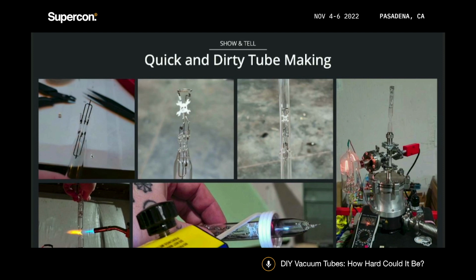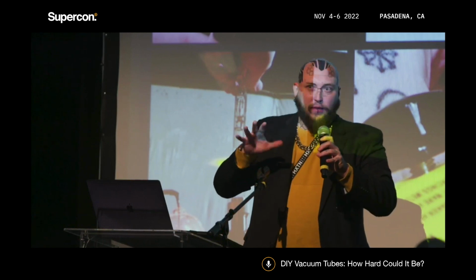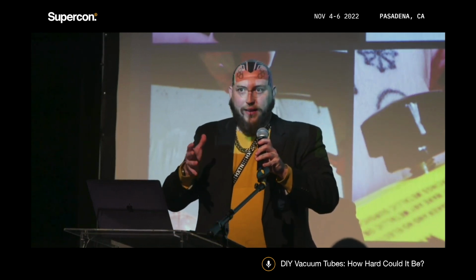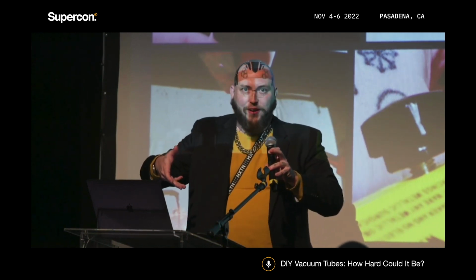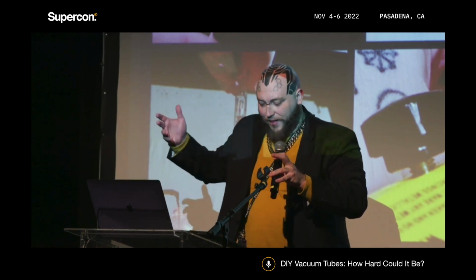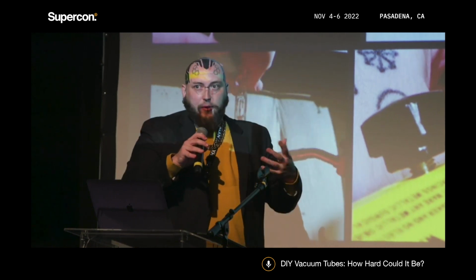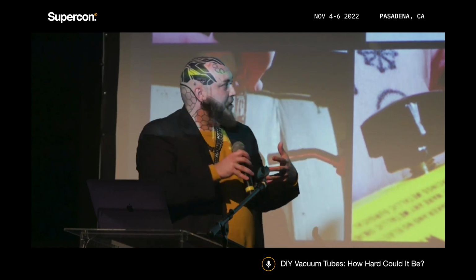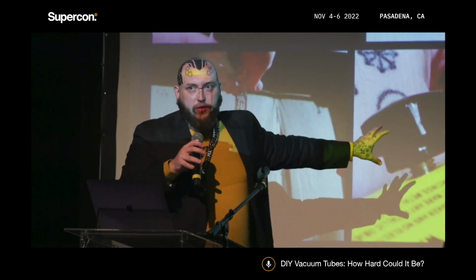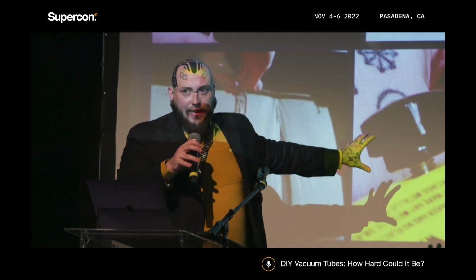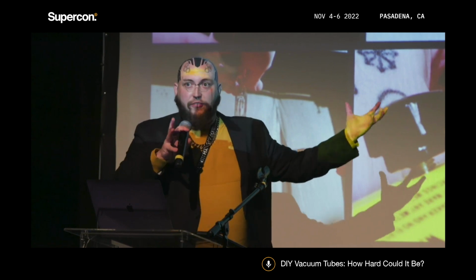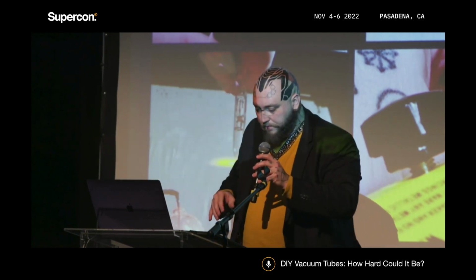So while this thing was on the vacuum rig, I was measuring 1 × 10⁻⁵ torr of pressure. That more or less is correct. I haven't calibrated that gauge controller. I got it, again, used from some college. But it's in the neighborhood. It's in the right order of magnitude, right? And then who knows what the pressure in the tube is now, because after I fired that getter, hopefully it actually dropped even below that.